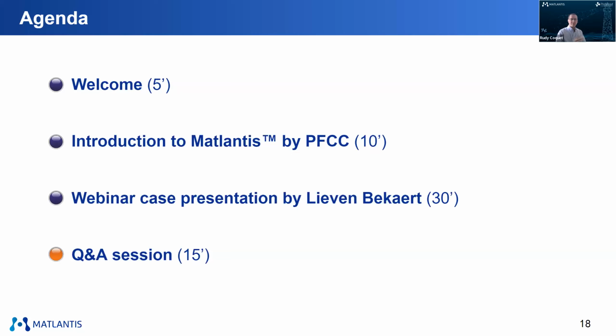The whole story dates back to the time when PFCC did not exist yet, and it was still PFN and ENEOS. Catalysis was at that time one of the most important topics. And we have some very nice case studies on that as well, where, for example, for syn fuel synthesis, you have a cobalt surface, and you study different metal promoters for this catalyst. Because Matlantis is so fast, you can actually screen thousands of configurations with different promoters.